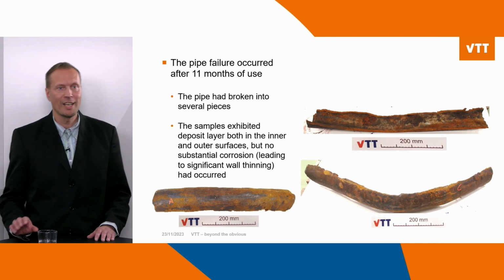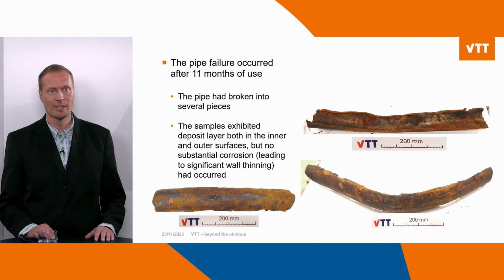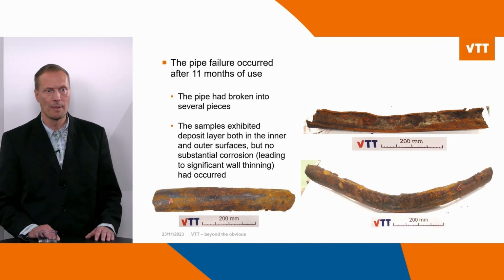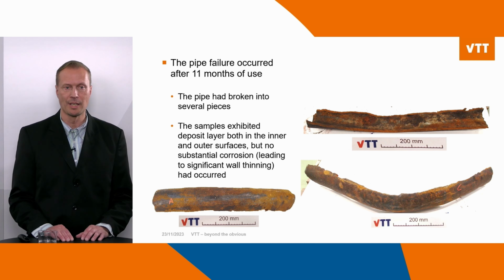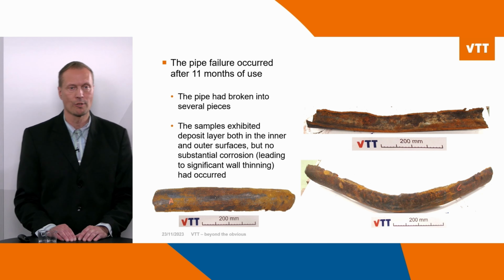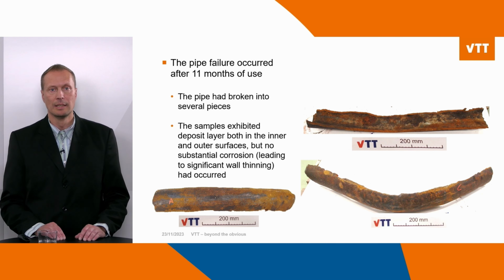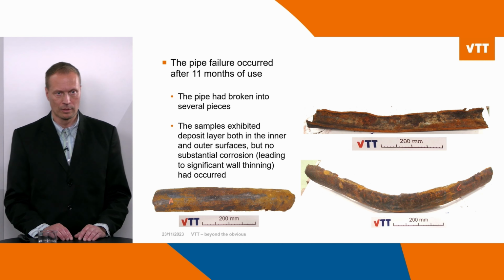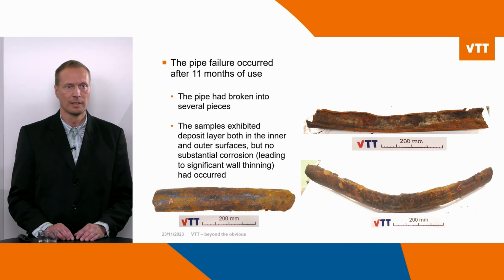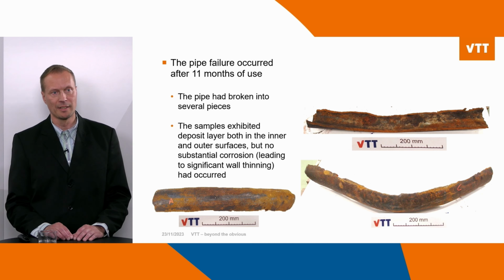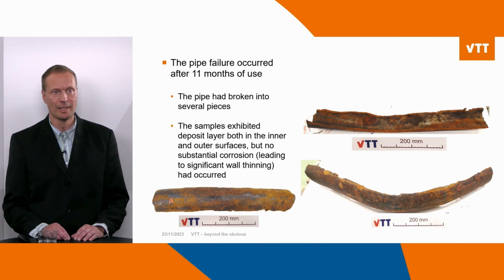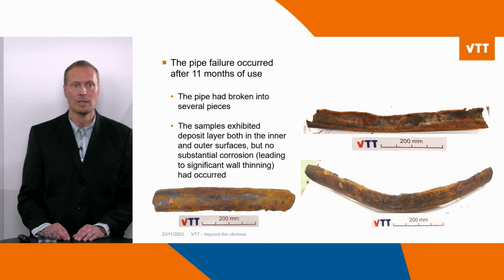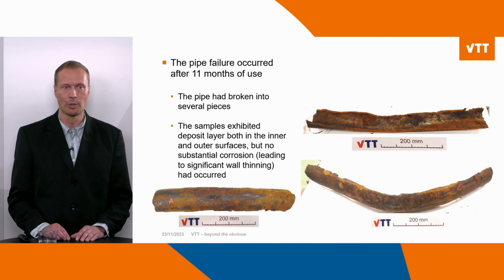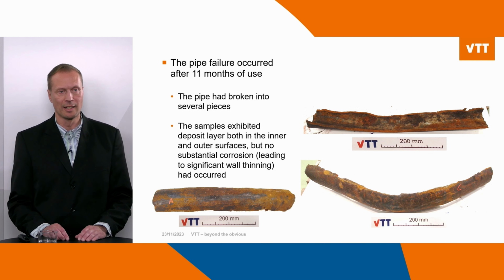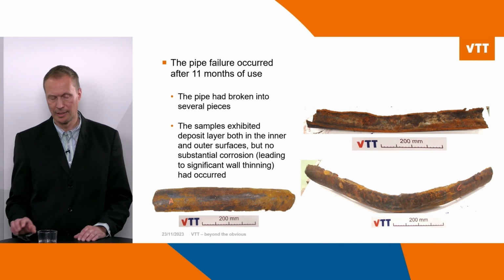So the pipe failure occurred here after 11 months of use and the pipe had broken into several pieces, so the failure was rather extreme. When we first look at the samples, it revealed that samples exhibited deposit layer both in the inner and outer surfaces, but no substantial corrosion which would, for example, lead to significant wall thinning had occurred in these samples.